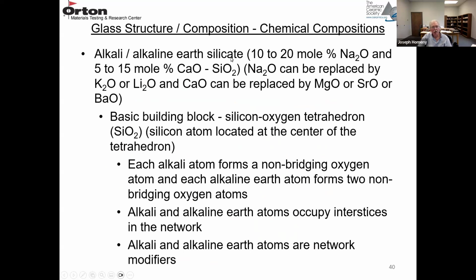Then you have alkaline earth silicates. So now you might have 10 to 20 mole percent Na2O, 5 to 15 mole percent CaO. And the Na2O can be replaced by K2O or Li2O, and the CaO can be replaced by MgO, SrO, or BaO. So your basic building block is still the silicon oxygen tetrahedron with the silicon atom located at the center of the tetrahedron. So each alkali atom, we already discussed this, forms a non-bridging oxygen atom. And then each alkaline earth atom actually forms two non-bridging oxygen atoms.